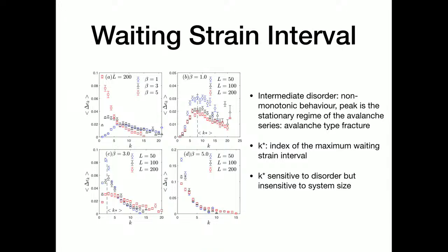So if we look at these disorder levels individually for different system sizes, we see that this peak location for beta equal to 1 that we saw here in the blue, if we increase the system size, it only lowers, but there is no change in this quantity that we are now referring to as K star, which is the index of the maximum waiting strain interval, and that seemed to be independent of the system size. This is also seen for beta equal to 3, where the peak is at a lower K star, but the K star seems to be more or less largely insensitive to the system size. And for higher beta but lower disorder, the monotonic acceleration towards final failure seems to be also seen for all the system sizes.